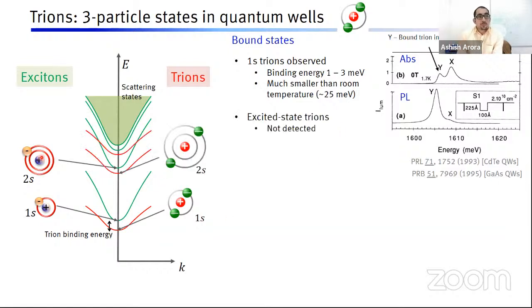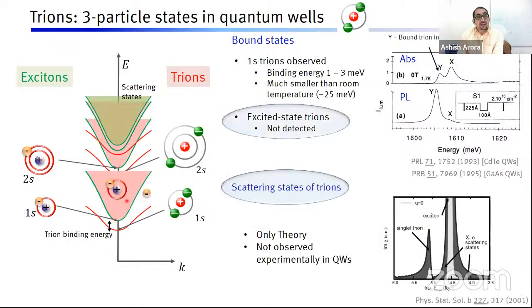However, we can also put an electron along with this 2s shell, and then we can have a doubly excited trion where both electrons are in the outermost shell. Now, these excited states of trions have not been detected so far before this work. Similarly, there can be scattering states of the trions where the electron can scatter from an exciton. These scattering states have been predicted theoretically in 2001. However, they have not been experimentally observed in quantum wells.